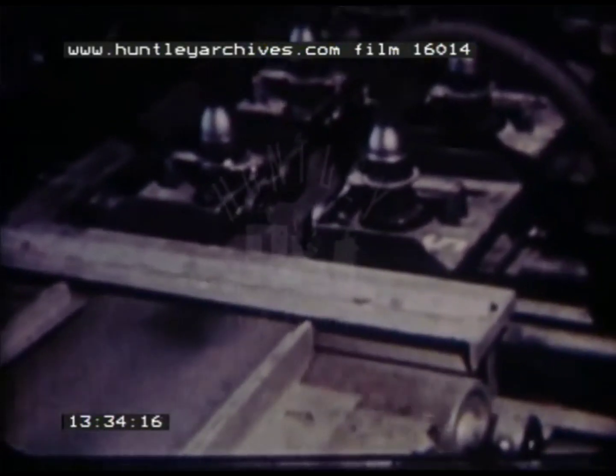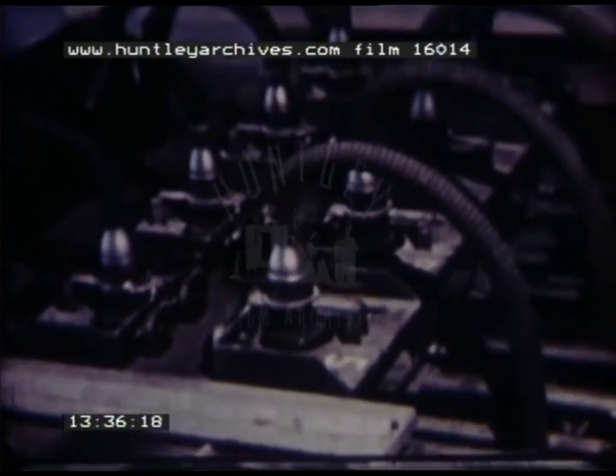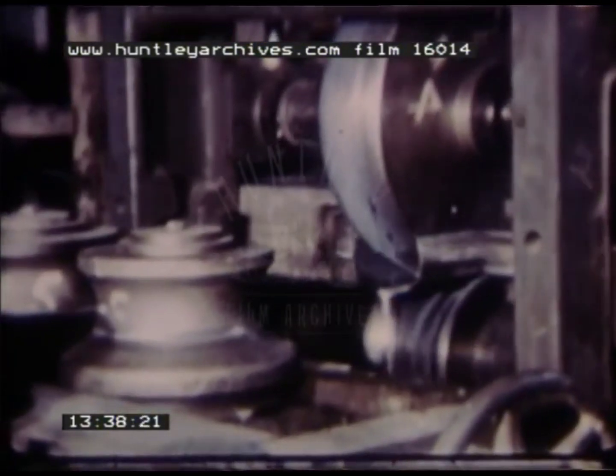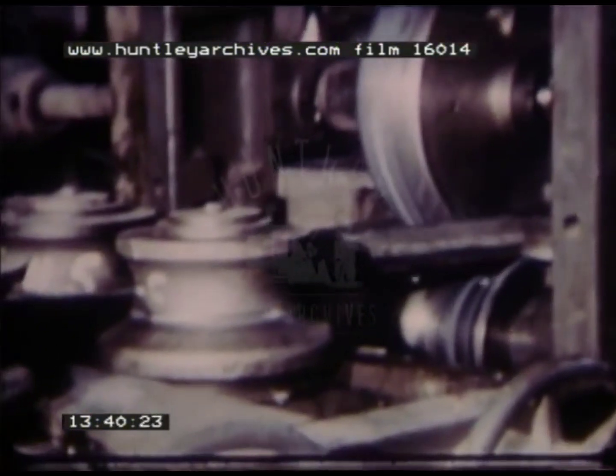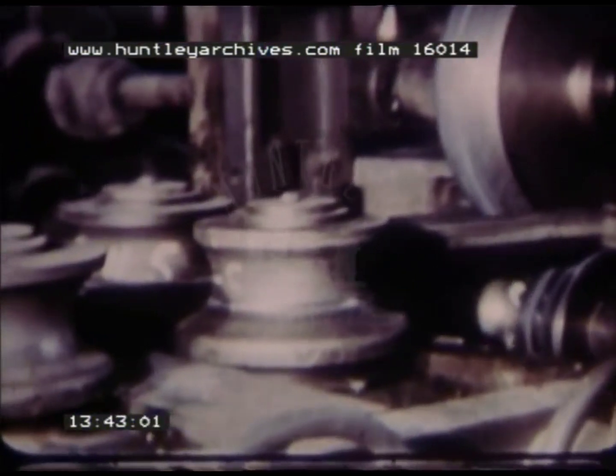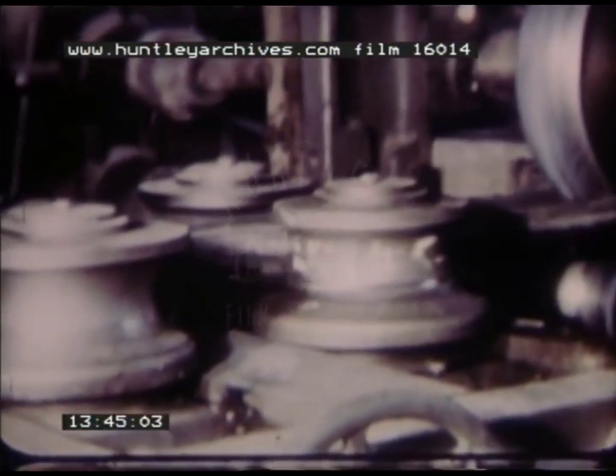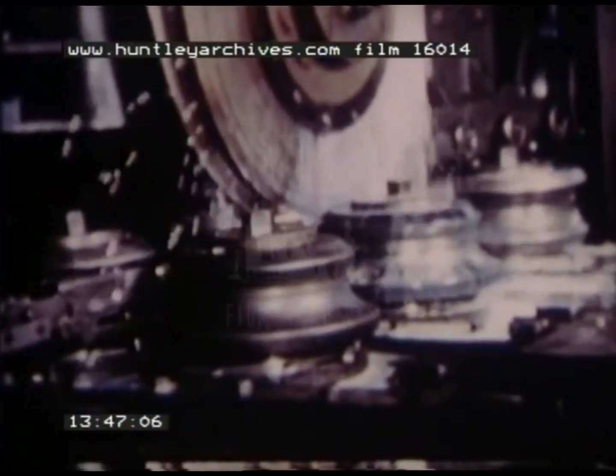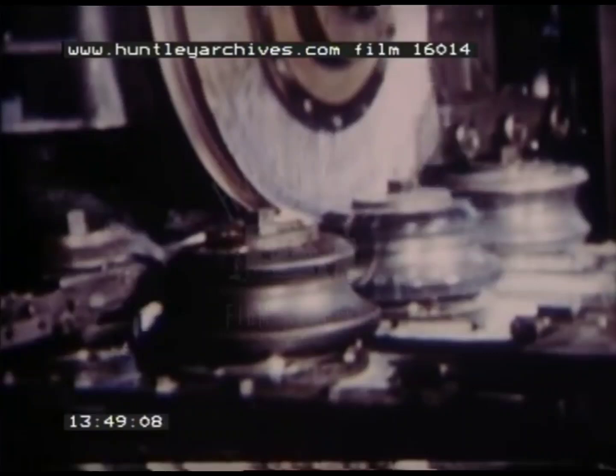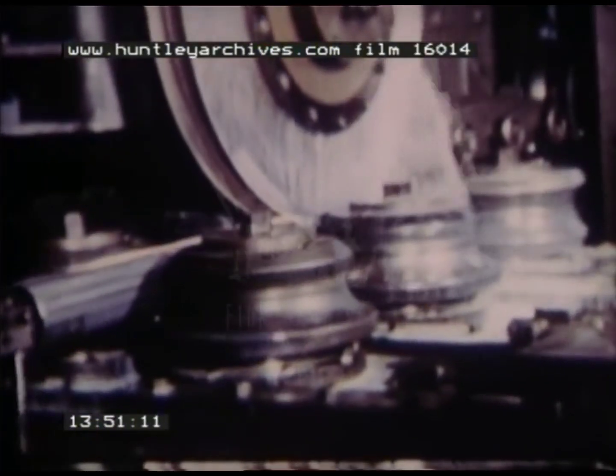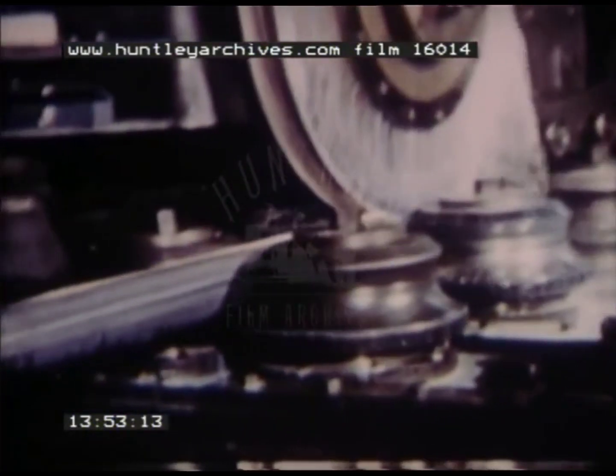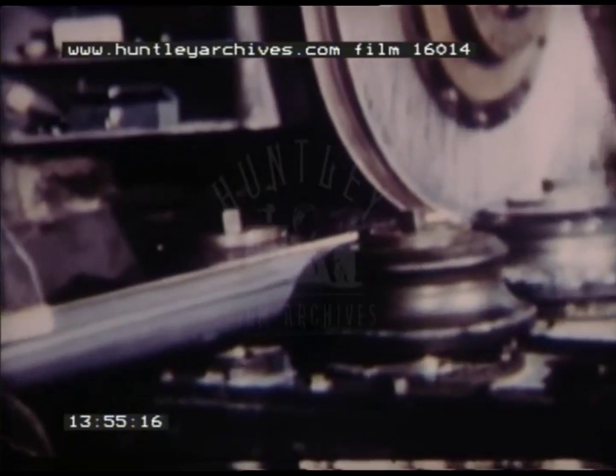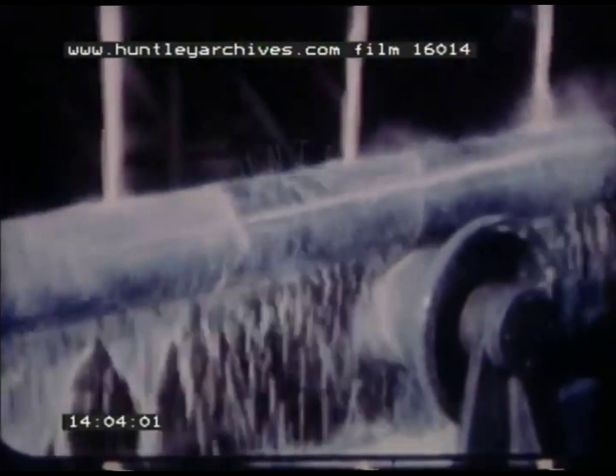Larger pipe, ranging up to 12 3/4 inches in diameter, is made from steel skelp in the electric weld mill. The skelp is sandblasted and edge trimmed, after which it is shaped into circular pipe in a series of forming rolls. The edges are butted together and welded electrically to form a strong leak-proof seam. This weld is stronger than the steel itself. The weld is then cooled under streams of soluble oil, after which the pipe is straightened, tested, and shipped to be used for gas, oil, and water transmission.